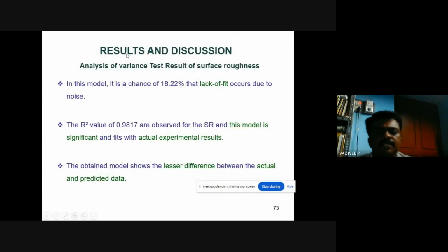The analysis of variance tests the results of the surface roughness. In this model, there is an 18.22 percent chance that the lack of fit occurs due to noise, and an R-squared value of 0.9817 is observed for the surface roughness. The model is significant and fits the actual experimental results, showing a small difference between the actual and predicted data.